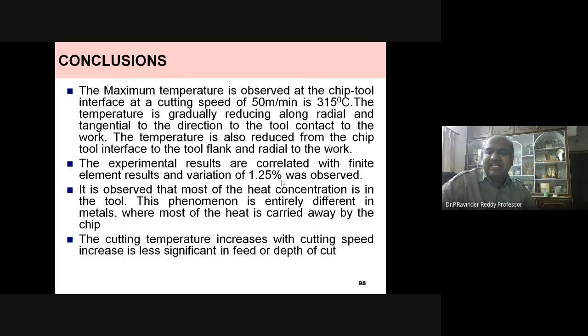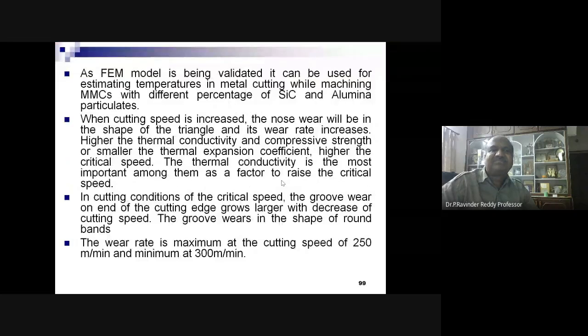The cutting temperature increase with cutting speed is significant, while that with feed and depth of cut is less significant. As the FE model is validated, it can be used for estimating temperature in metal cutting while machining MMCs with different percentages of silicon carbide and alumina particulates. When cutting speed is increased, the nose wear will be in the shape of a triangle and its wear rate increases. The higher the thermal conductivity and the compressive strength, or the smaller the thermal expansion coefficient, the higher the critical speed. The thermal conductivity is the most important among them as a factor to raise the critical speed.